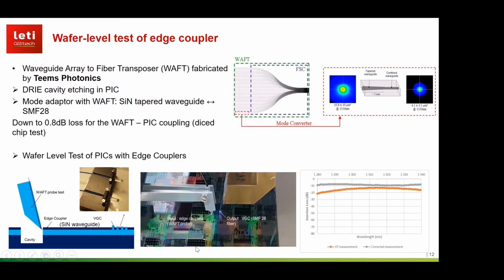And so we have demonstrated a solution to test the edge coupler devices, or the edge coupler itself, at the wafer level. So the schematic is here, and we use a WAFT, waveguide array to fiber transposer, which is fabricated by Teem Photonics. It has glass waveguides with a mode which is matched to the mode at the output of the silicon nitride waveguide. And we can have this WAFT in front of the waveguide in the PIC, the photonic integrated circuit, thanks to a cavity etch that we etch anyway, because when we dice the chip, we etch in the middle of the cavity, then for the packaging. So with this solution, we can test devices with edge coupling scheme very easily on a prober. So it's very interesting, I think, to show that.